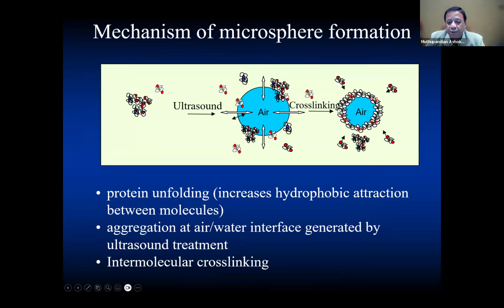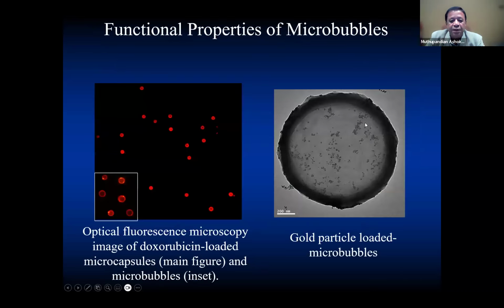So the proteins adsorb on either the air-liquid or liquid-liquid interface, and then we simply cross-link them to form these microspheres. In here, for example, the microspheres are loaded with a drug called doxorubicin, and the red dye that you see is due to the doxorubicin, which can be used, for example, for cancer treatment.